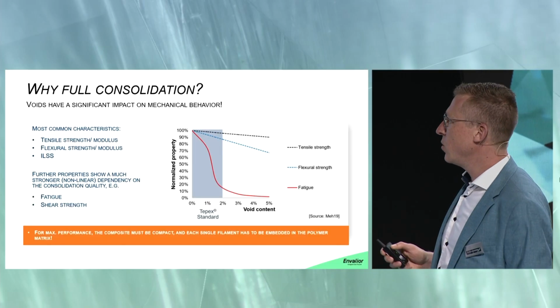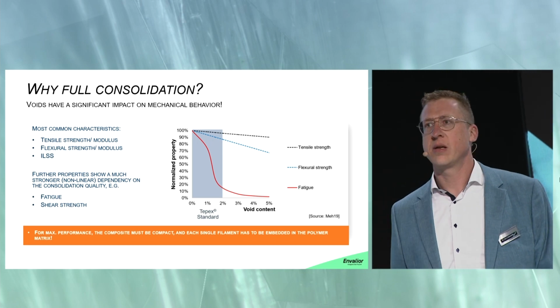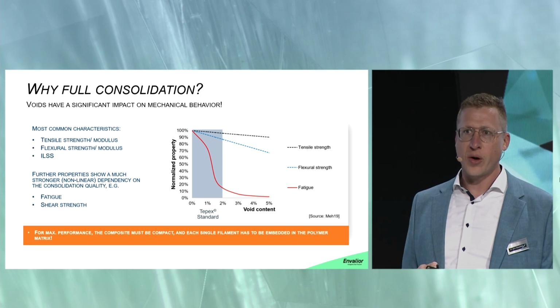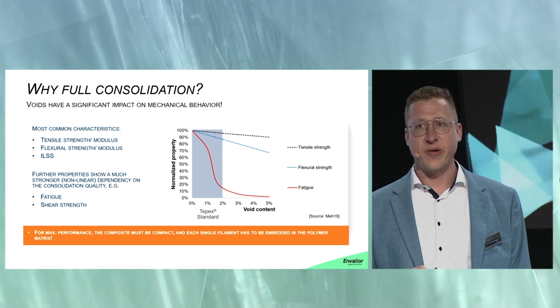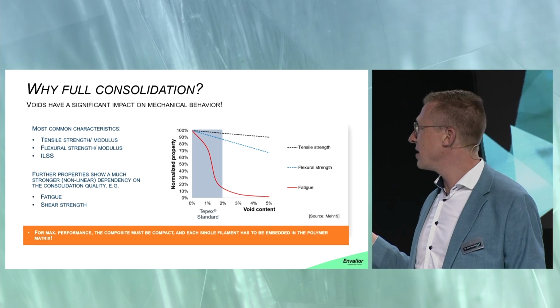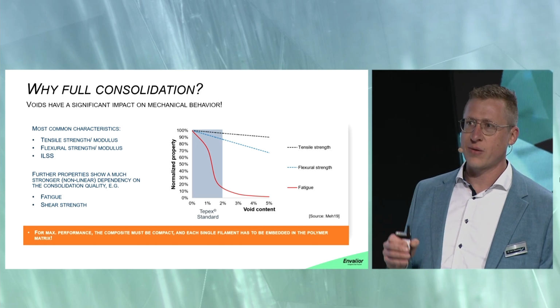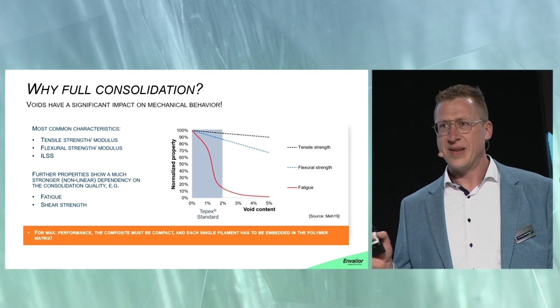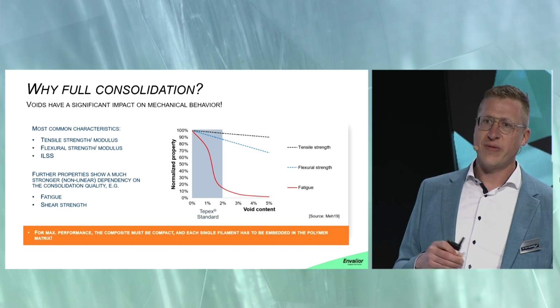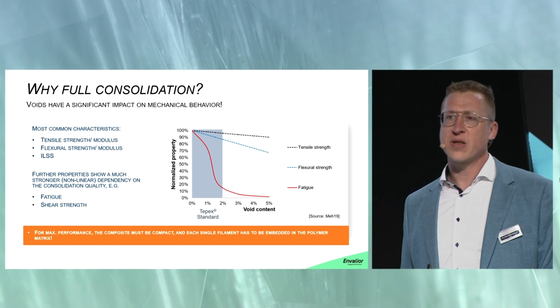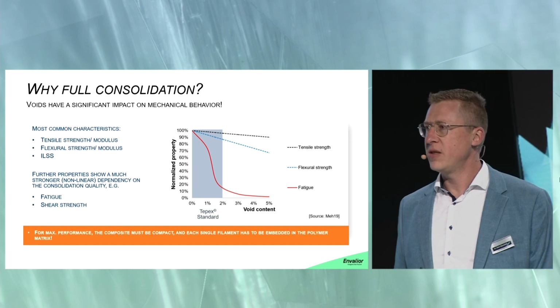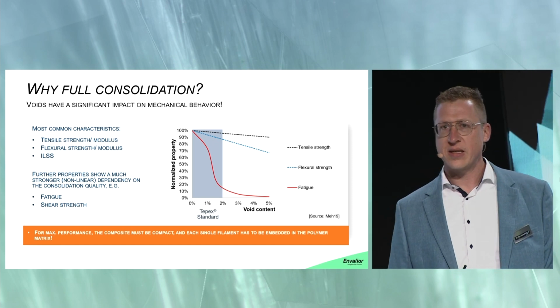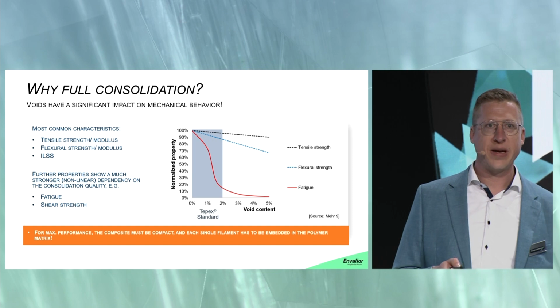Why is it important to get rid of these voids and of these inclusions, and in particular to bring the melt to the filament? You will see that when you don't have this full consolidation, there is a huge drop in the mechanical performance. I would say the tensile strength and the flexural strength drop is maybe still acceptable, but especially in terms of fatigue and especially in terms of shear strength, you will have a huge drop if you don't consolidate the material in the best possible way.